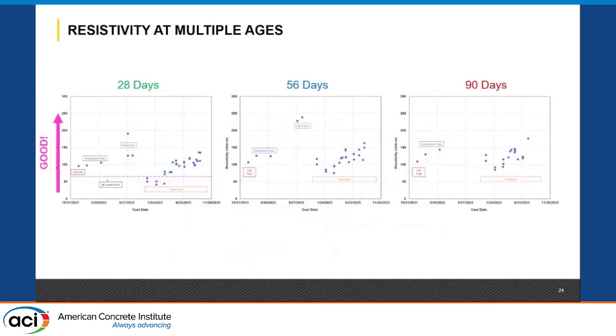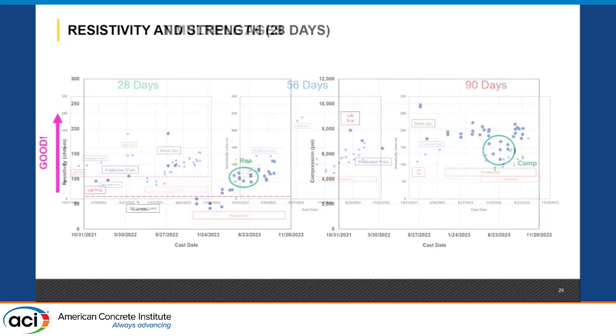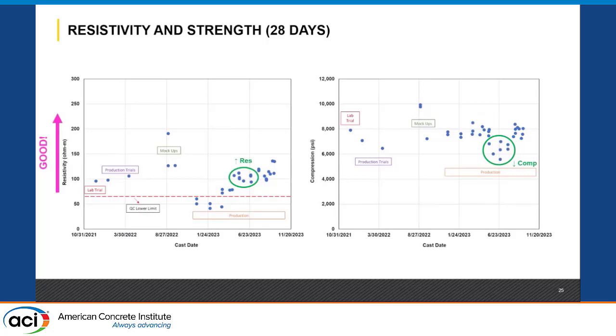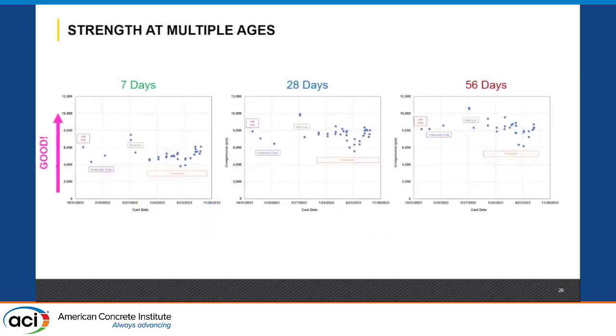I can't. We saw that the trend for resistivity matched at 28, at 56, and 90 days. So we know for sure that something was going on with this concrete that made it have low resistivity consistently. We compared it with strength. In broad terms, durability is not the same as strength, but good durability should also come with good strength. And we saw that sometimes your low compressive breaks have good resistivities. So that was not even matching. There may be some drops in strength because of seasonal effects, water demand in the hotter months, and so on. But in any case, no real correlation with strength. That was the key aspect. And we also see that strengths did not see the big dip that we saw in resistivity.